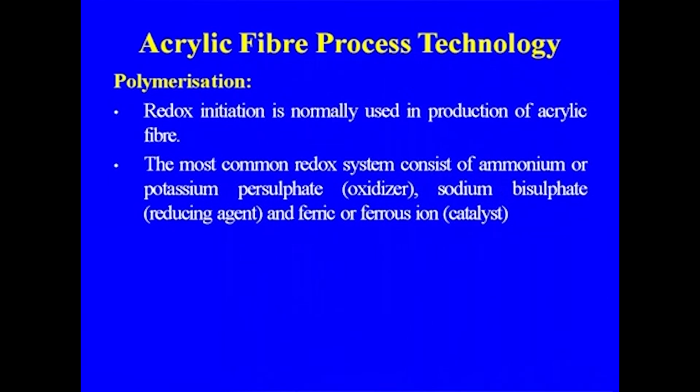Redox initiation is normally used in the production of the acrylic fiber. The most common redox system consists of the ammonium or the potassium persulfate, sodium bisulfite and the ferric or the ferrous ion.